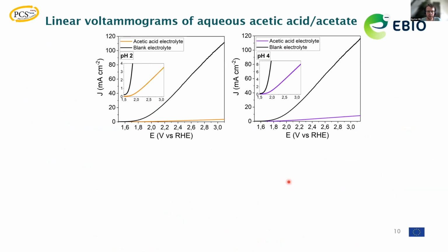So before going into the online product analysis, I would like to briefly point out what the current-potential behavior in the different electrolytes actually is. If you use a blank electrolyte, which is a pH 2 electrolyte of just an acid, where the conductivity is rather high, you can see that at a certain potential, at around 1.8 volt, the oxygen evolution reaction kicks in. And with the acetic acid in place, basically a pure acetic acid electrolyte, we have quite low conductivity of the electrolyte, so we are limited very much in the current densities that we can achieve. Of course, with increasing pH that is going to be slightly better, and we already reach higher current densities, but still you couldn't observe any of the plateau regions that I've indicated previously on the slides in the potential range that has been investigated here.